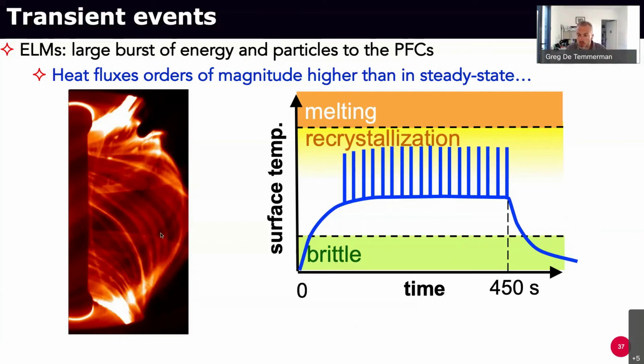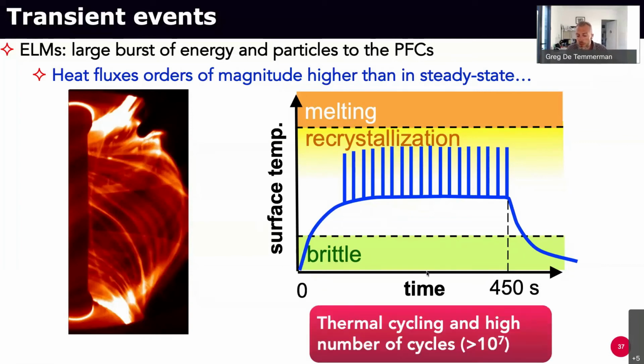So you dump a lot of energy onto your materials for a very short amount of time, and then you do that quite a lot. So if you look at the temperature of your surface, you will see just the baseline temperature, and then you will see all those spikes on top of that. And of course, that is a lot of thermal cycling that you have to worry about, especially because the number of cycles, at least in ITER, is expected to be at least in the 10 million range. This is really a large amount of time where the material can be cycled.